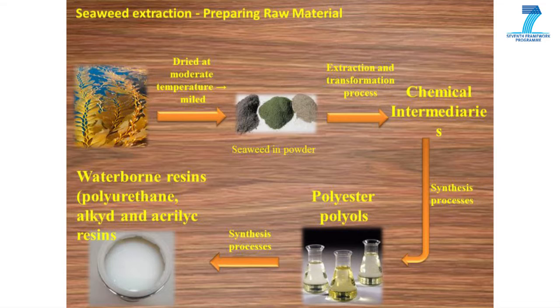The seaweeds were collected from beaches and coasts all over the world. To obtain a homogeneous mass, the seaweeds should be firstly dried at moderate temperatures and then milled to obtain a higher surface-to-volume ratio. The extraction of polysaccharides is typically performed by treating the seaweed raw material with hot aqueous or acidic solutions at temperatures ranging from 70 to 100 degrees Celsius for several hours using, for instance, a Soxhlet device. The result was chemical intermediate, that is, any chemical substance produced during the conversion of some reactant to a product.